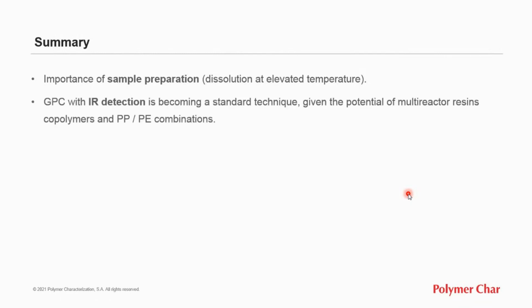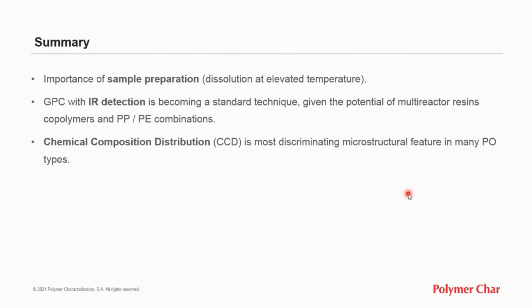So that brings me to the summary of the presentation. We have seen the importance of sample preparation because we need to dissolve at elevated temperatures, so we need to take some precautions: reduce the dissolution time, control the dissolution time, add nitrogen to purge and remove the oxygen during dissolution. That helps to preserve the high molar mass fractions. Then the GPC with multiple detection, which is becoming a standard technique given the potential of multi-reactor resins, copolymers, polyethylene, polypropylene combinations. We have seen that the chemical composition distribution is the most discriminating microstructural feature in many polyolefin types.